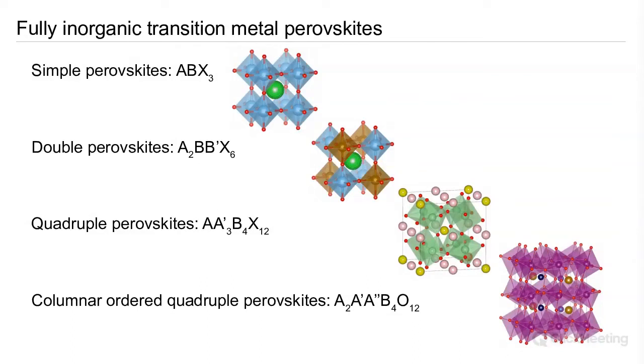There are the so-called quadruple perovskites, which I spent quite a bit of time working on, where we have a 1:3 ratio ordering at the A site. And then more recently, we've done quite a bit of work on the so-called columnar-ordered quadruple perovskites, where the A site is in fact split into 3 different symmetry-inequivalent sublattices that form columns running along the c-axis. So the structural flexibility really goes a long way beyond the simple perovskites.